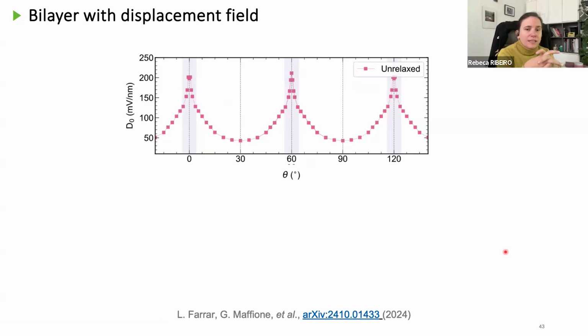Okay, so we can see in this curve what we'll expect intuitively, because it's also a very intuitive result, is that when we are aligned, atoms are closer to each other, so they will feel a stronger electric field, which is the case here. So you can see it increases every 60 degrees, but this is periodic and it does not look like our previous curve. But you will also realize that this is an unrelaxed system. This means that this is just rigid graphene on top of rigid boron nitride.